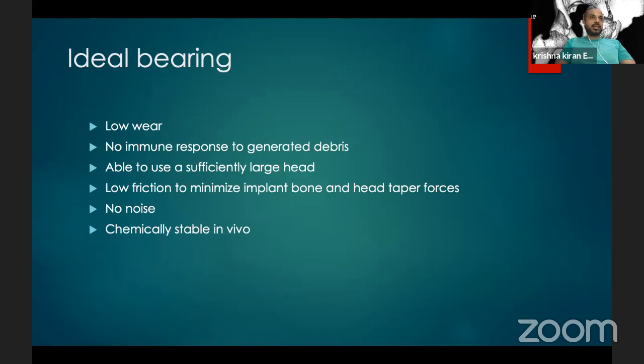And we had the zirconium experiment, which failed badly because of a phenomenon called phase transformation, where the zirconia underwent phase transformation and fractured at 7-8 years following implantation. So although the early results were good, the implant, because it had phase transformation and was chemically unstable inside the body, had higher failure. So we don't want such experiments to happen again.